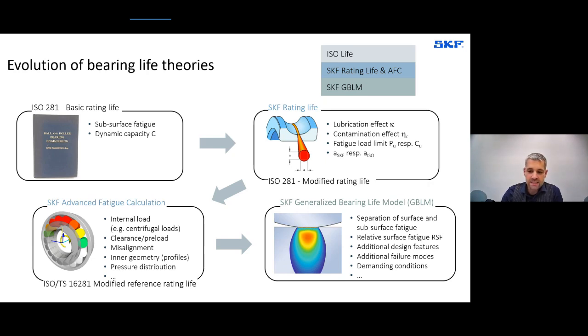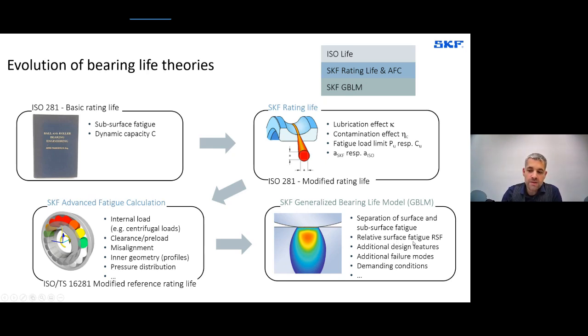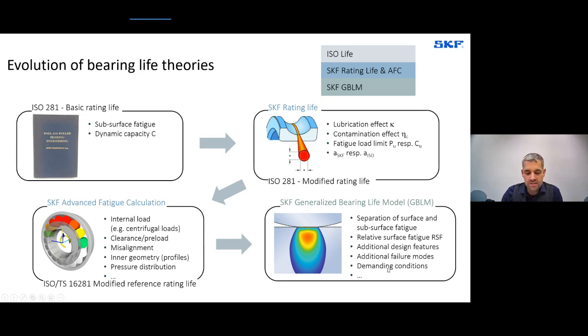At SKF, new scientific models are developed for surface and subsurface failure regions. Adding new physics to an 80-year-old framework is mathematically and physically very difficult. So in GBLM, we separated surface and subsurface effects to continuously integrate new models. Additionally, GBLM introduces the RSF — Relative Surface Fatigue — an indicator showing whether you have a surface or subsurface issue, allowing more realistic quantification of design features and failure modes.